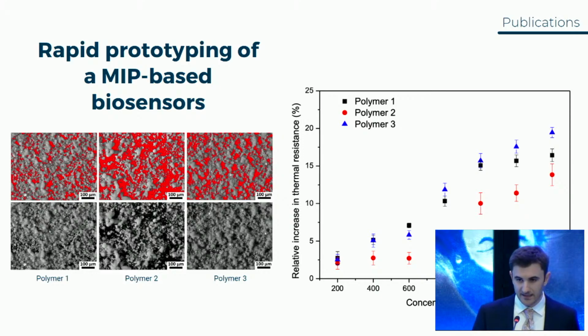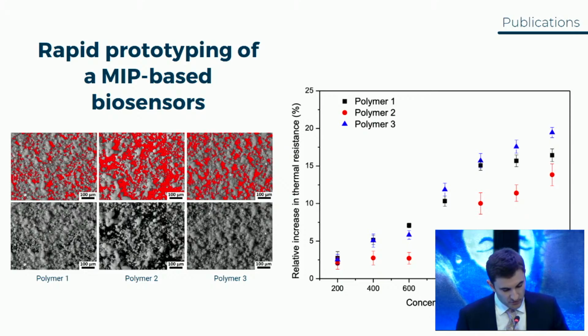In detail, one of the main characteristics that we chose to analyze was the surface coverage of the receptor layer, because of course it influences directly the amount of area that is available for the target to be bound to the receptor layer. So we finally show that the type of polymer, so the different polymer film used in this application, does indeed have an influence on the sensor performance.